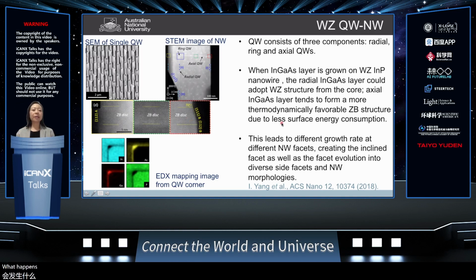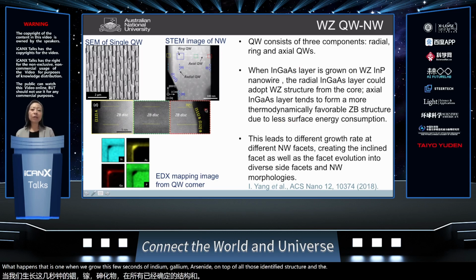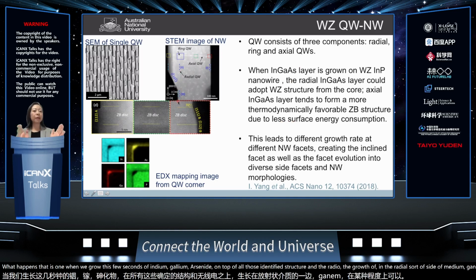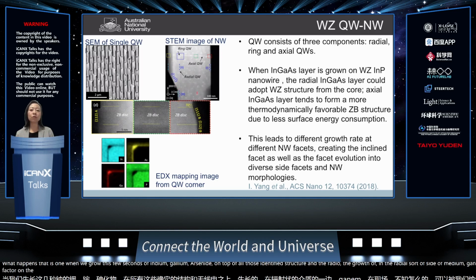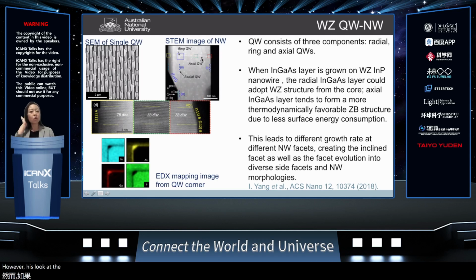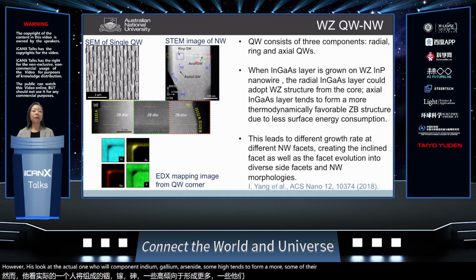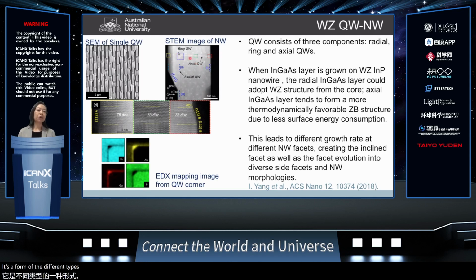when we grow these few seconds of indium gallium arsenide on top of our wurtzite indium phosphide structure, the growth on the radial side of indium gallium arsenide could very happily adopt the wurtzite structure from the core. So if you look at the TEM, here is all wurtzite structure, right? However, if you look at the actual quantum well component, indium gallium arsenide, it tends to form the more thermodynamically favored zinc blende structure, a cubic structure basically. And this is because of a low surface energy, right?